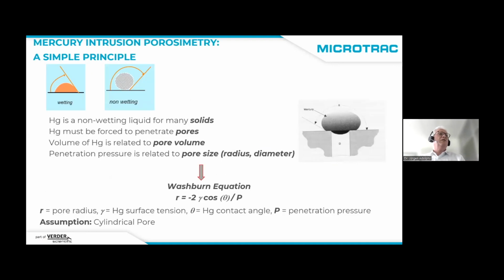What is the principle behind it? We are dealing with mercury as a non-wetting liquid, and we need pressure to press it into the pores of our systems. So that is one value we get, the pressure. And with this equation from Washburn, we can easily calculate the pore radius from the pressure, knowing the surface tension of mercury and the contact angle, always assuming a cylindrical pore. And another way, it's like a capacitive method. We also know the volume of mercury which is intruded into the pores. We then get the value of the pore volume.